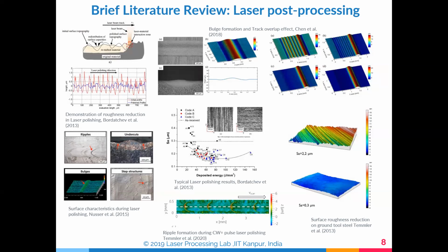When different types of polishing are done, it tries to reveal the surface. So you will have a rough surface, ripple surface, undercut, and you will also have step structures. When we look into bulge formation or track, you can see that graph. This is the bulge formation. Generally, bulges are formed when the ripples are formed and moved. It tries to solidify and then get the ripple shape. So this is bulge formation and track overlap.